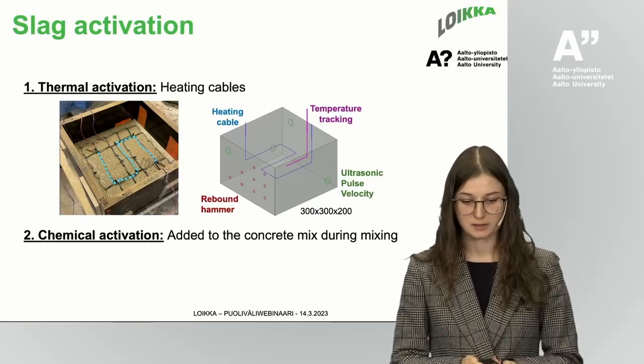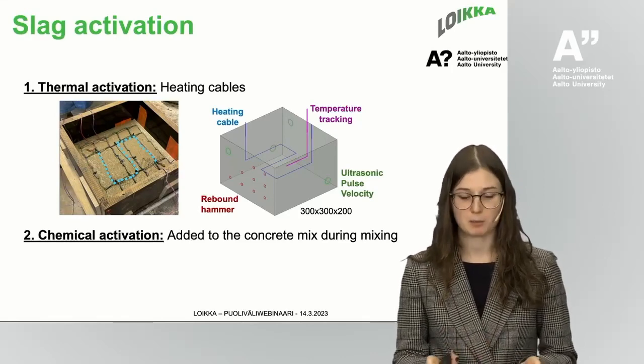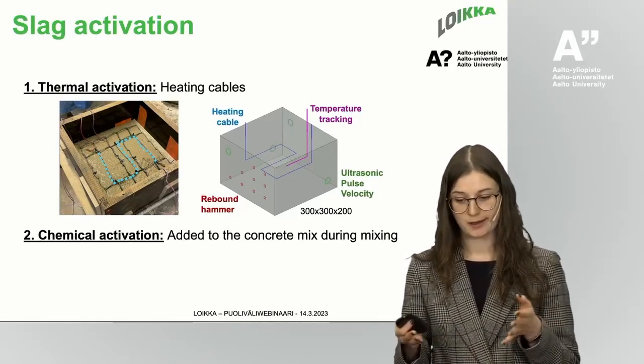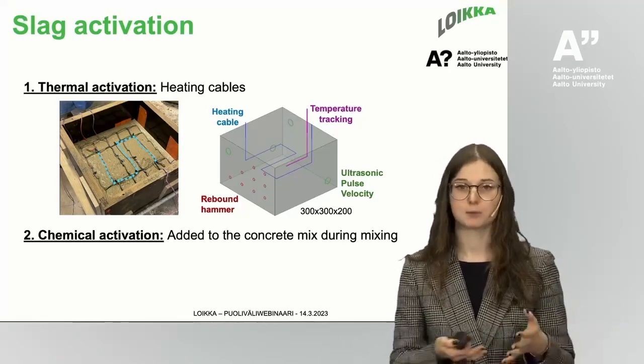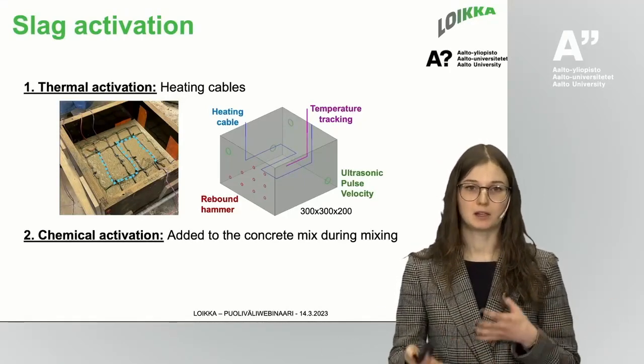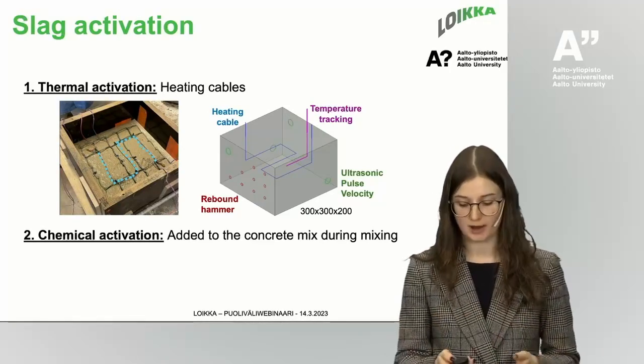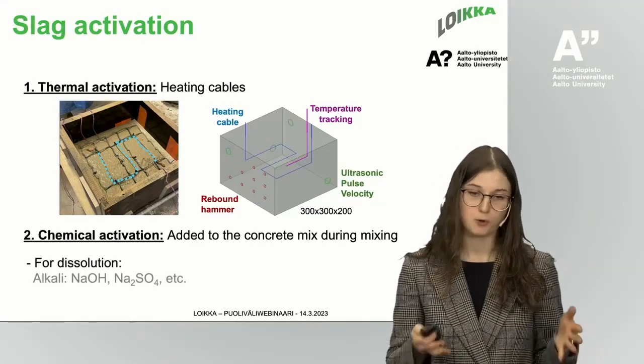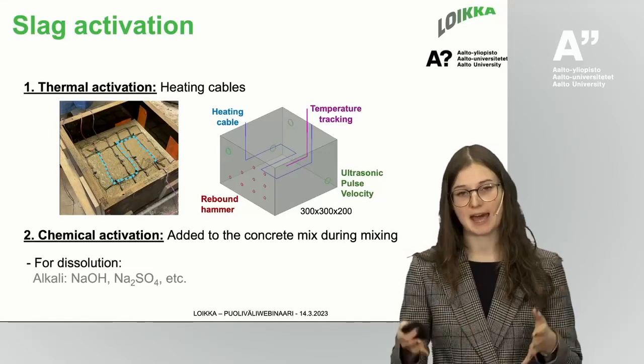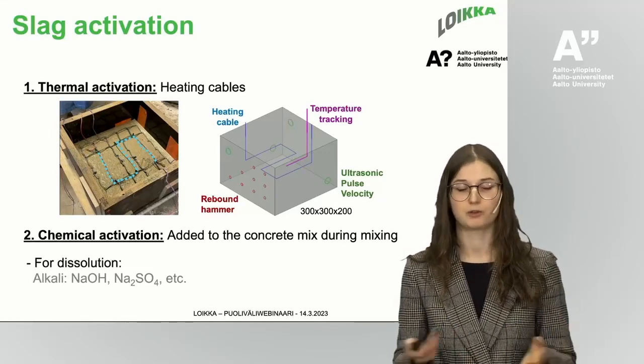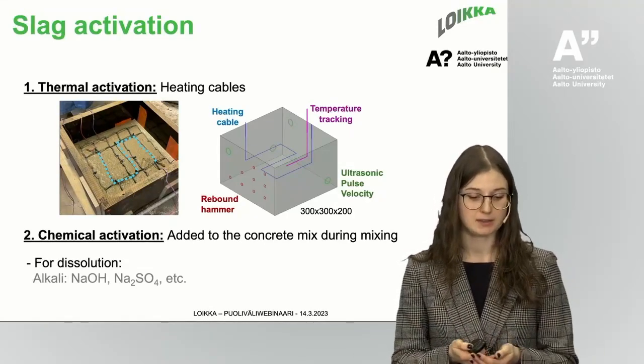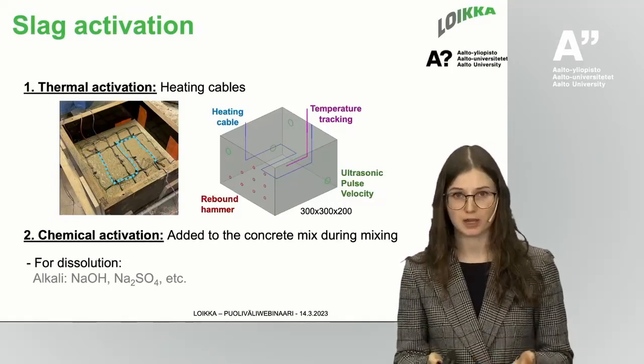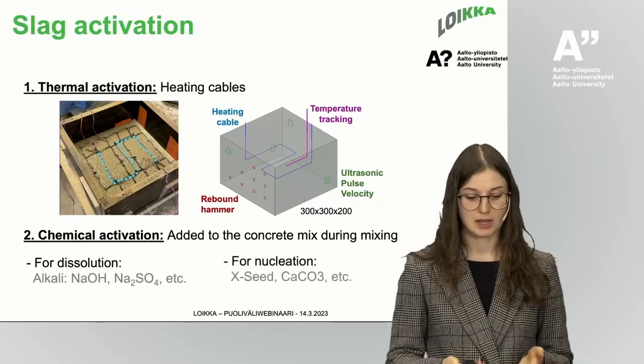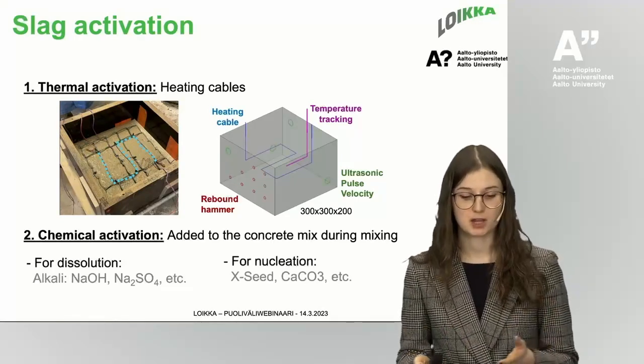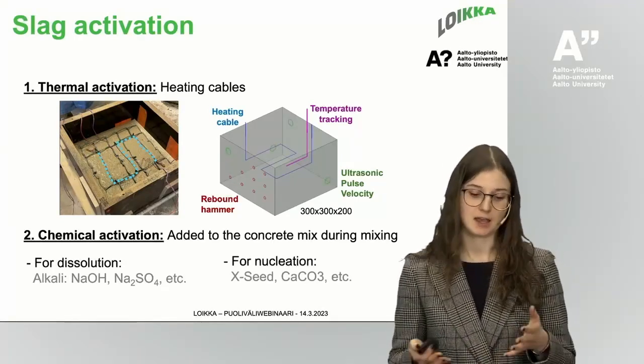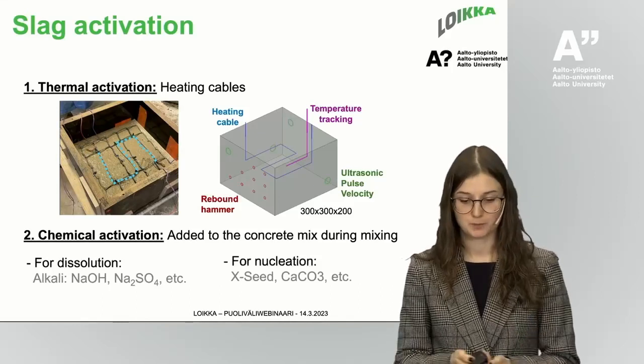So this is one method that was used, and another one is chemical activation. The admixtures, the chemicals that we were using, were added mostly in liquid form during the mixing time. One group of the chemicals was added to affect the dissolution, as I already mentioned, and mainly sodium hydroxide and sodium sulfate were used. To affect the nucleation, X-seed and calcium carbonates were used.